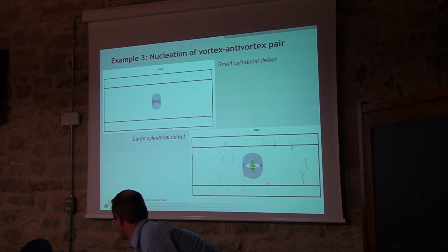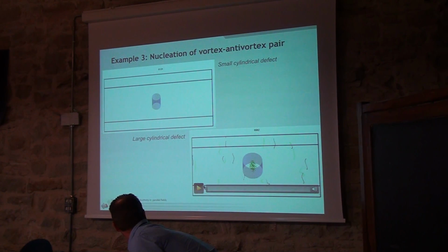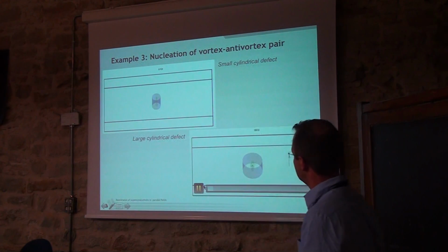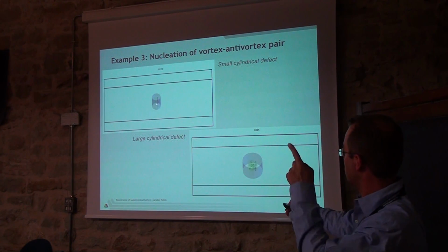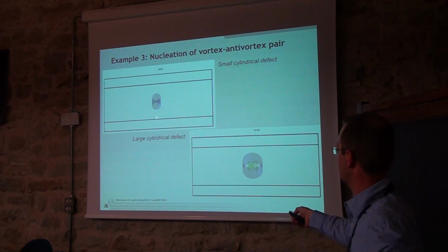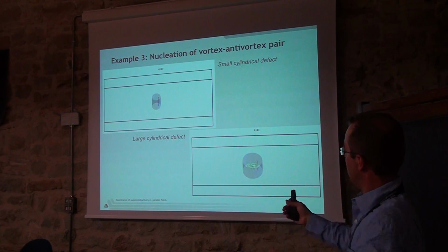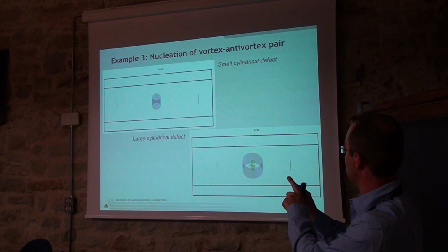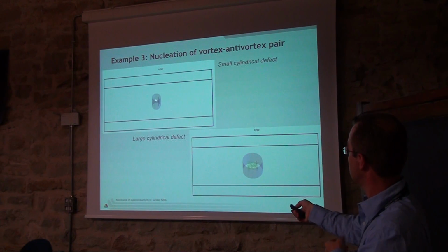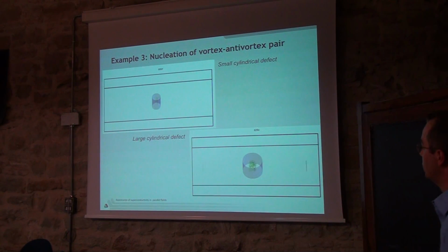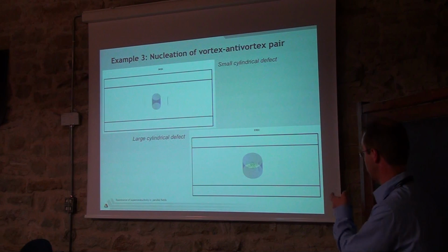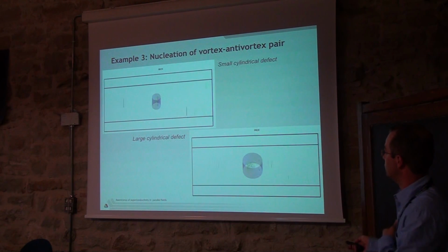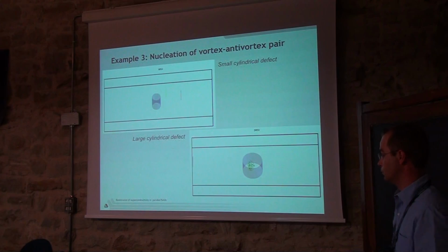relaxation going on. This should also move. This is just a cylindrical defect, and you see here, for example, the vortex and anti-vortex lines, which are colored differently by their chirality. They split due to fluctuations, and if you increase the field or the current, they separate and leave your inclusion. Depending on the size, you see there's a lot of noise going on because the amplitude of your order parameter is too small to detect anything. But you see how useful this can be.